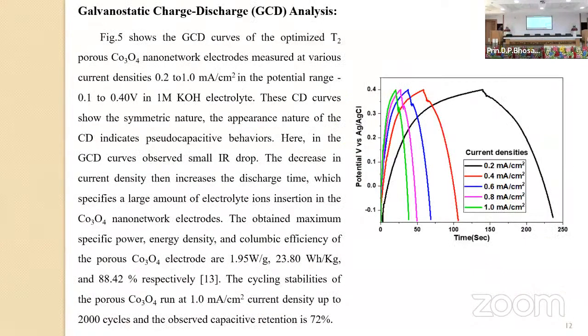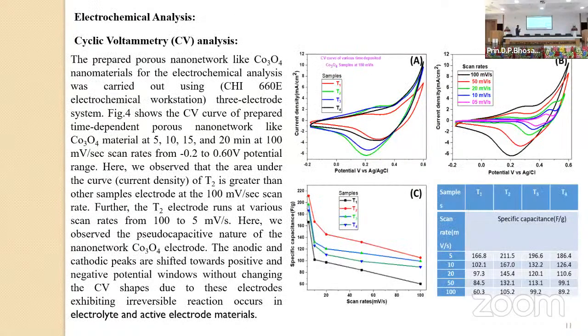Next. Okay, then the main application is the supercapacitor, that is the electrochemical application. First of this is the CV curve, the cyclic voltammetry analysis. I have shown the time-dependent parameters, that is the CV curves for 5 minute, 10 minute, 15 minute and 20 minutes. But here the most redox reaction is in the 10-minute deposition time of cobalt oxide nanomaterial, at various scan rates, that is 5 to 100 millivolt per second.